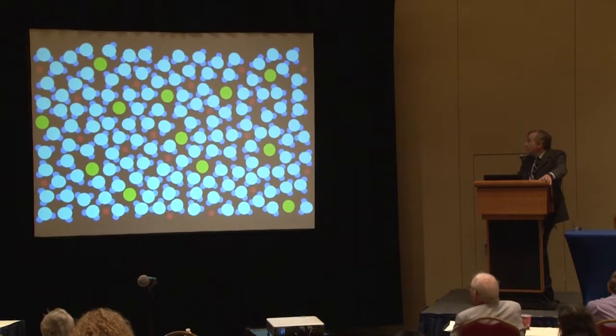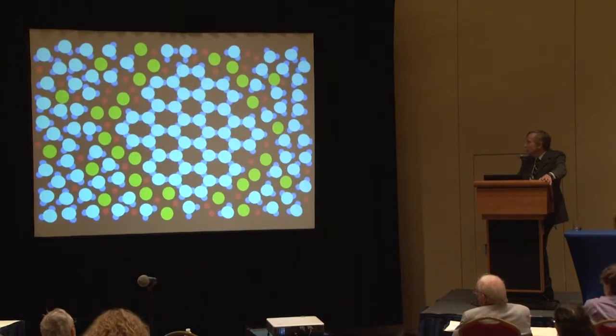So conceptually, on a molecular scale, you've got your solution of randomly organized water molecules and solutes, and on a very localized scale, homogeneous nucleation occurs. Homogeneous nucleation involves mostly rotational reorientation of water molecules next to each other with a minimum of diffusion.